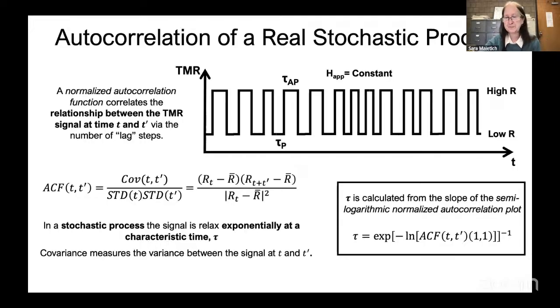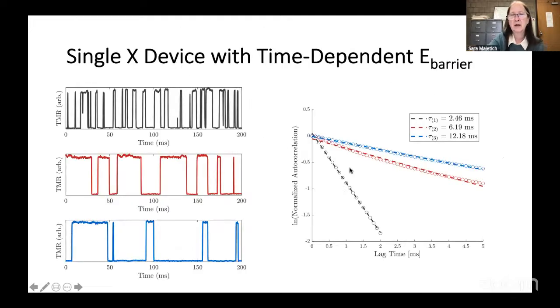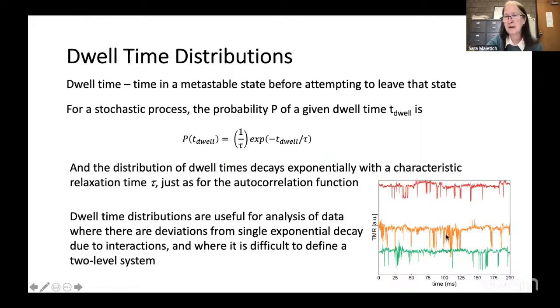One way to quantify this, and we've used this earlier for isolated devices, is to do an autocorrelation where you take the time-dependent resistance signal and subtract the average resistance, multiply that by the time-dependent resistance at a later time, and normalize it. And this function decays exponentially, and there's a characteristic decay time. In fact, if we take windows where we think the telegraphing is relatively uniform, we see something that's single exponential or close to single exponential, maybe a little curvature in here, with relaxation times on the order of a few milliseconds. But you can't do this for the other types of devices, the Y devices, where the autocorrelation just gives a mess.